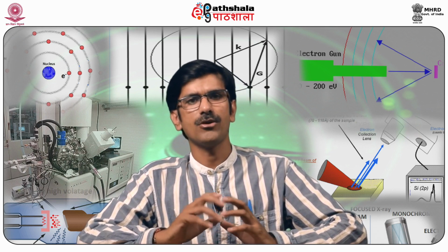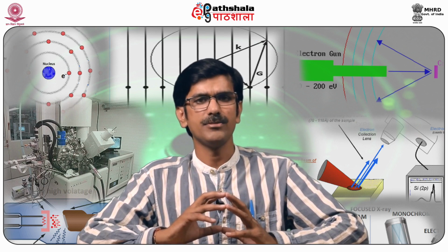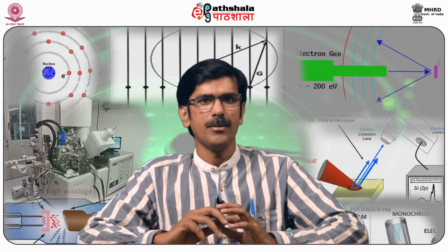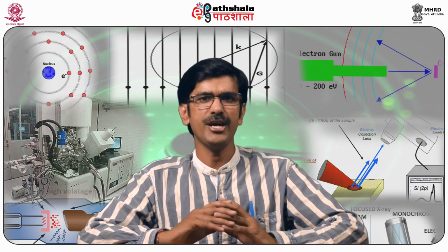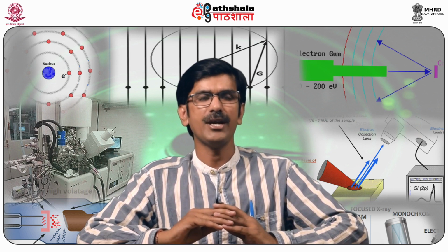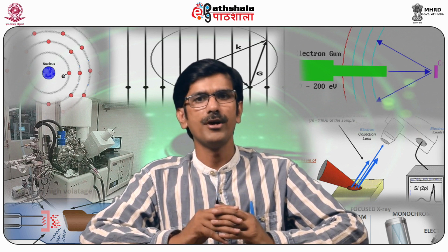Using nitrogen adsorption isotherms, information on size distribution in the micro, meso, and macro porosity range, approximately 0.5 to 200 nanometer, can be obtained. Barrett, Joyner, and Halenda, which is popularly known as BJH, is a classical pore size model developed in 1951. This is most widely used for calculation of the pore size distribution over mesoporous and part of the macroporous range.